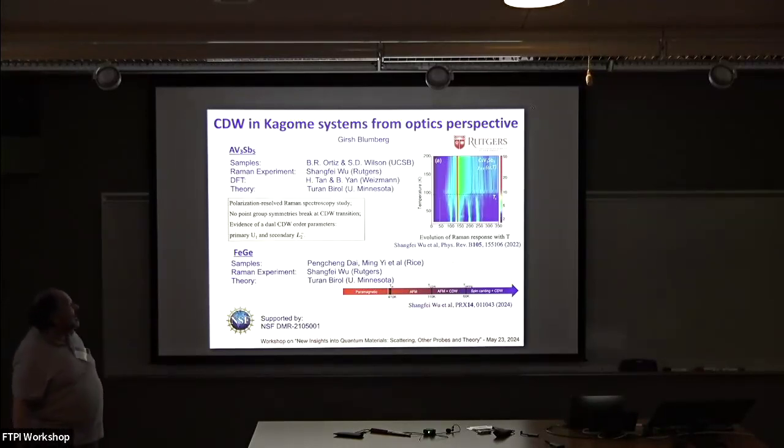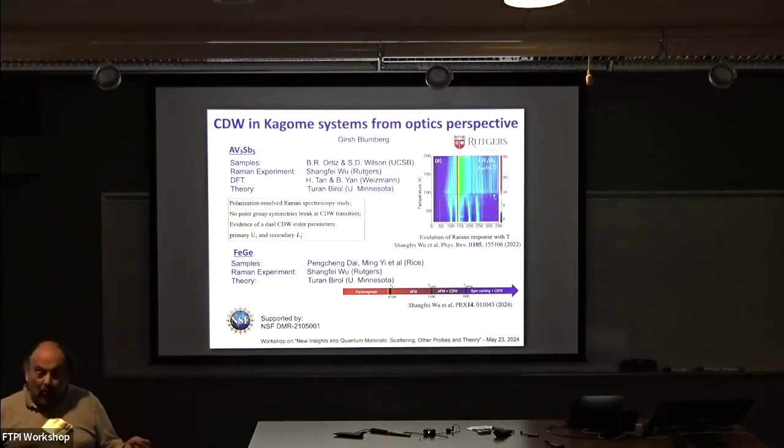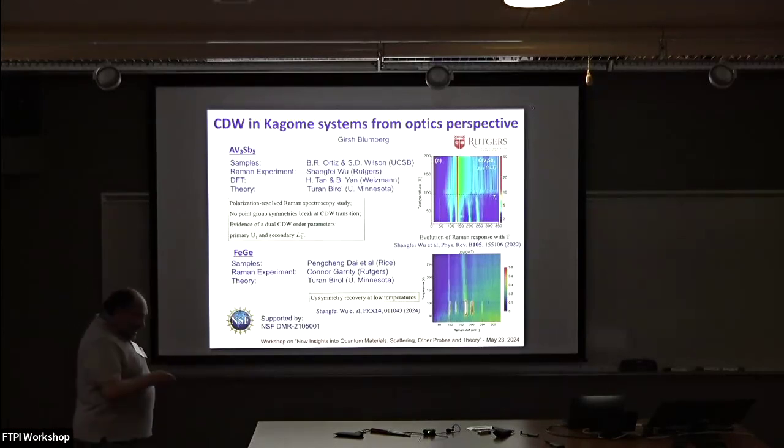And we learned from this system that the order parameter is not at all trivial. It's not one broken symmetry, but at least three broken, and there is a combination in the Landau expansion, and the trilinear term allows coexistence of different order parameters. All this popped up from this study. And from this study, the story was even more interesting, because what we learned is that when we go, let me go back.